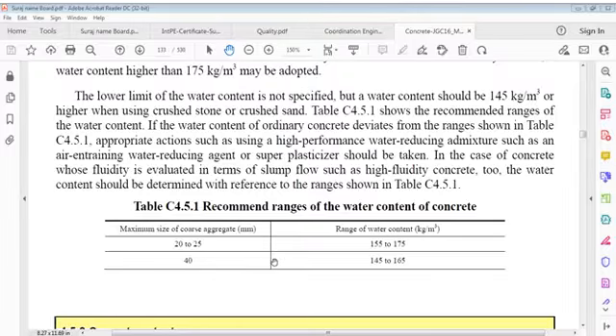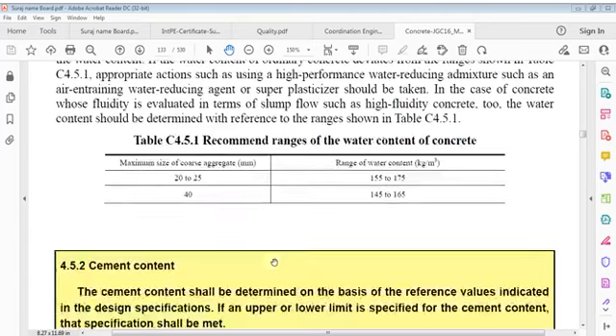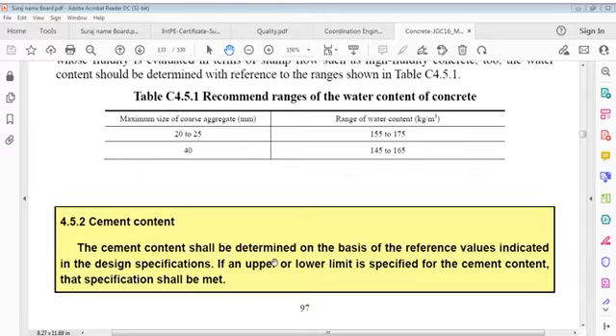The lower limit of water content is not specified, but the water content should be 145 kg per cubic meter or higher when using crushed stone or crushed sand. This shows recommended ranges of water content. If water content of ordinary concrete deviates from the ranges, appropriate actions such as using a high performance water reducing admixture such as an air entraining water reducing agent or superplasticizer should be taken. In the case of concrete whose fluidity is evaluated in terms of slump flow, such as high fluidity concrete, water content should be determined with reference to the ranges. Recommended ranges of water content for concrete: when the maximum size of aggregate is 20 to 25 mm, it is 155 to 175 kg per cubic meter, and for 40 mm it is 145 to 165.